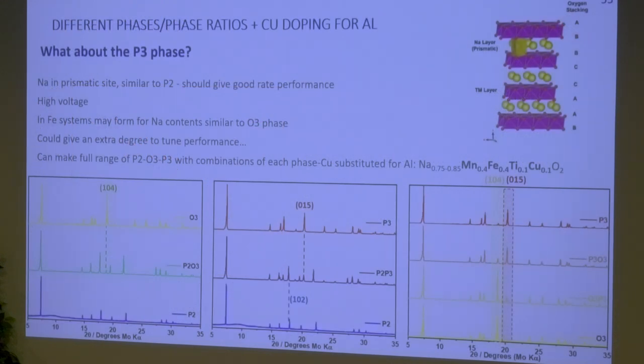I've got 5 minutes, so we've also looked at P3 materials as well, particularly with the discovery that people say P3 is a low temperature phase. We took a sample, heated it to higher temperature. What happened was we got more P3 instead of less. So don't believe everything you read in scientific papers.